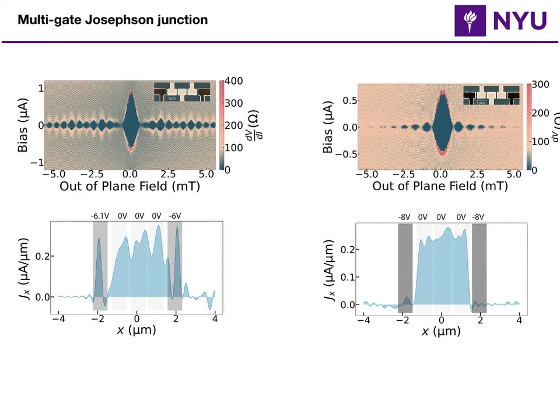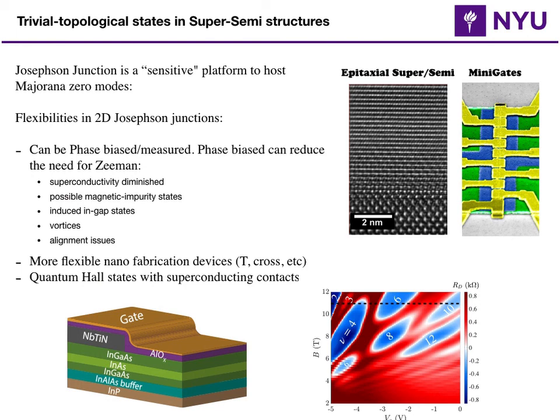So to get the proper picture here, we can deplete the edge mini gates, and then you can see on the right hand side we can recover a very normal looking, textbook Fraunhofer pattern with a very nice current reconstruction, which is mostly uniform. For this particular device, the aluminum thickness was too thick, so we didn't have the critical field of about 1.2 Tesla that I showed you earlier. But the new generation of devices are made with very thin aluminum, so hopefully we will have some of these devices in magnetic field and explore the new ideas around fusion and readout.